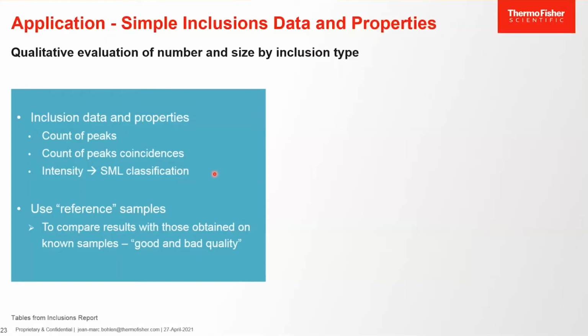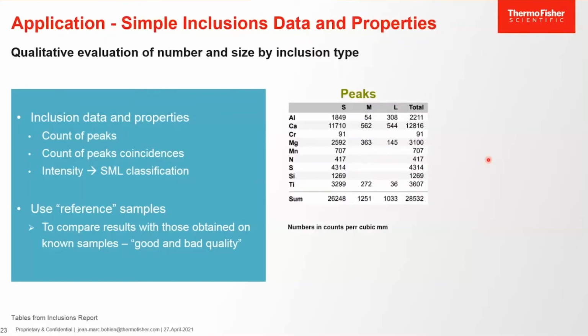The normal way to work with this kind of data is to use reference samples. In other words, compare results with those obtained on known samples, typically good ones and bad ones, in terms of the inclusion content. You have here an example of determination of number of peaks for low alloy steel samples. You see different elements that have been evaluated in terms of small inclusion number, medium size inclusion number, and large size inclusion number, for total number on the right side. These numbers are per cubic millimeter.